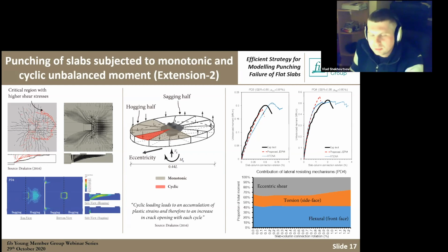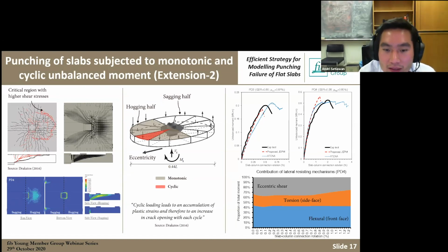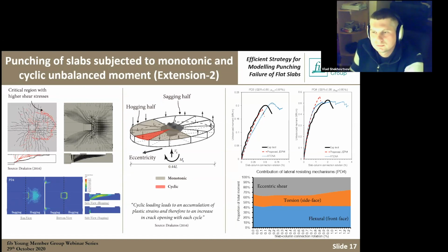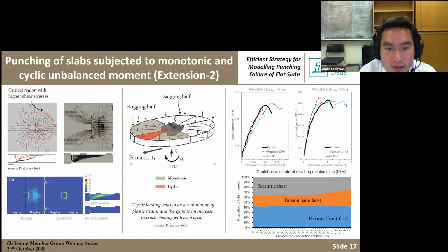But what is the layer of the reinforcement? Is it only the reinforcement ratio? It's modeled as an equivalent plate with equivalent thickness. For example, if you have a diameter 16 bar at 100 millimeter spacing, you can calculate the equivalent thickness by dividing the area by the spacing. So you get a thin steel plate in between the layers. You model the reinforcement as an individual layer, as a steel plate with equivalent thickness.